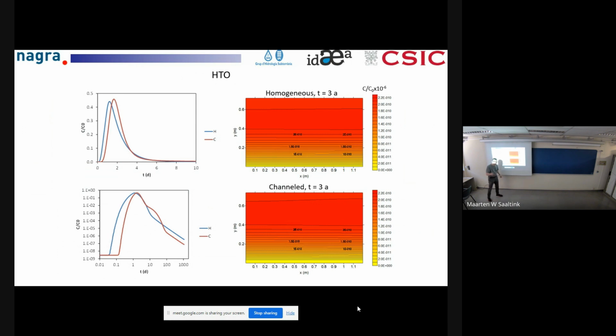So basically, even if it has diffused into the rock, the tracer has diffused out again after 3 years. So you have two curves, blue and red. Blue is the homogeneous case, so the fracture filled with fault gouge, and the red is the channel case. So you have this open channel connecting the two boreholes, bounded by rock matrix on one side and fault gouge on the other side.